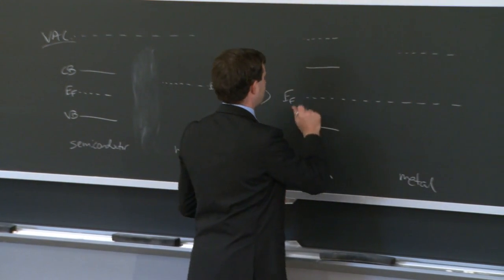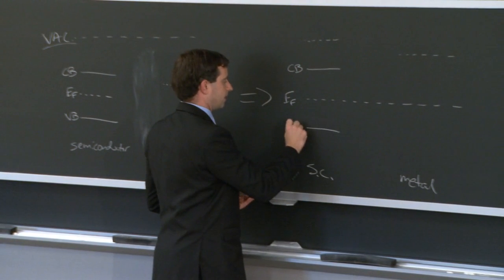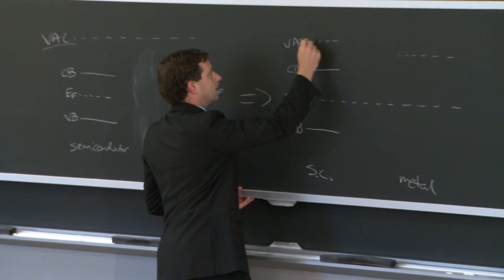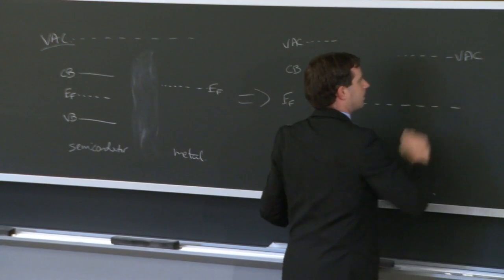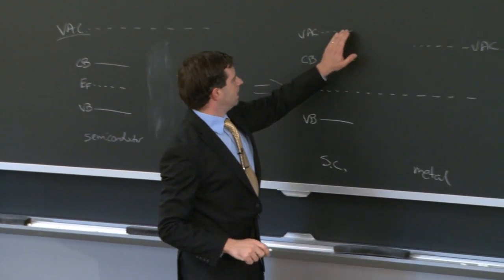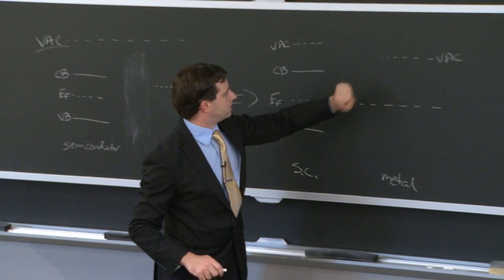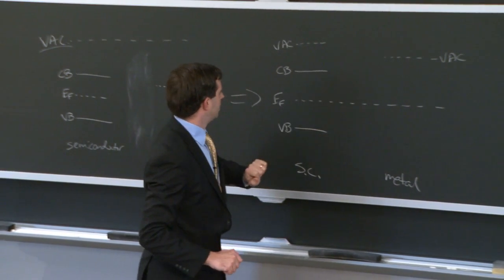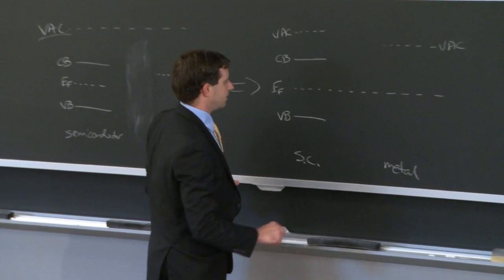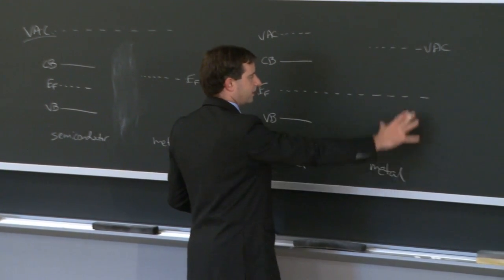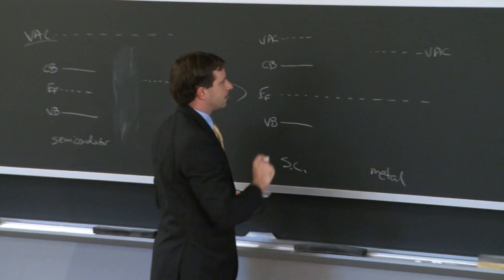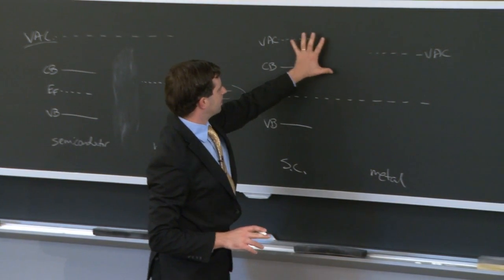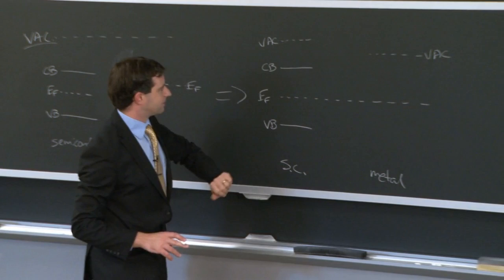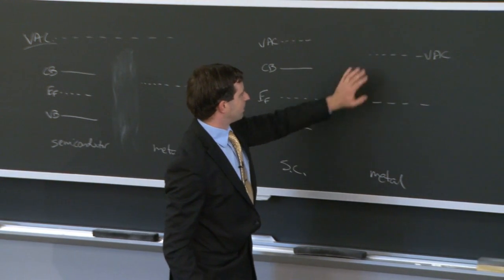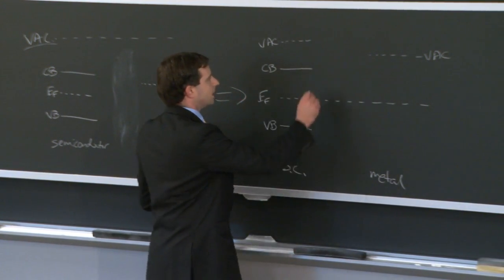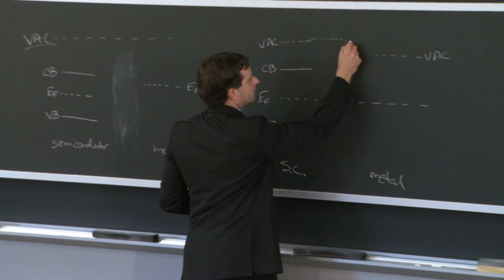This is the Fermi energy. This is the conduction band. This is the valence band. This is the vacuum level in the semiconductor, the vacuum level in the metal. And like we just described, the vacuum level has to be continuous. There has to be a continuity throughout. And so what we see here at the interface, since the density of charge is very high in the metal, but lower in the semiconductor, there's going to be band bending at the interface, and there's going to be a lot more bending of the bands in the semiconductor than there will be in the metal as a result of the difference in charge densities. And so what you'll see is something that looks like this.